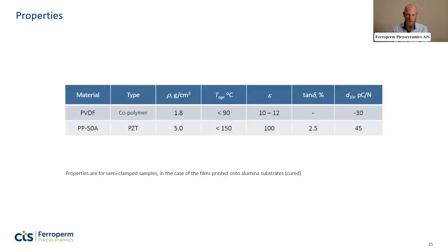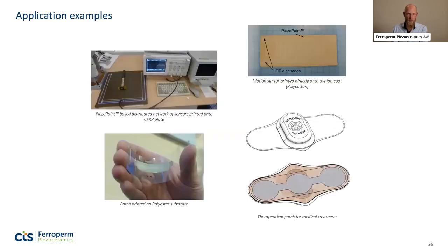These are just a very small selection of properties that we're able to achieve. So D33 in the range of 40, maybe 45 picocoulombs per Newton. We have a fairly high dielectric constant compared to other electroactive polymers. And in this case, it's compared to PVDF, which is the other flexible piezoelectric material that comes to mind when talking about these applications. So we think we have an edge with this material, and we've even tried to use it in certain demonstrators and applications.